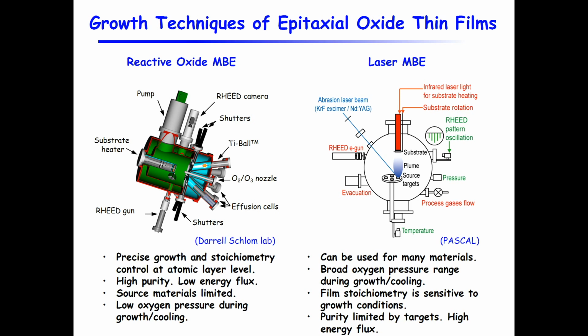Pulsed laser deposition is another technique, and laser MBE is a sophisticated version of PLD that does pulsed laser deposition under MBE conditions. It's more versatile. You just shine the laser on the target of the material you want to deposit, and that generates a plume and deposits on the substrate. It can be used for many materials, and it can work with a much broader oxygen pressure range. The problem is that people found the stoichiometry, although you can roughly reproduce the target stoichiometry in the substrate, is not exactly the same, and it depends on the growth conditions.